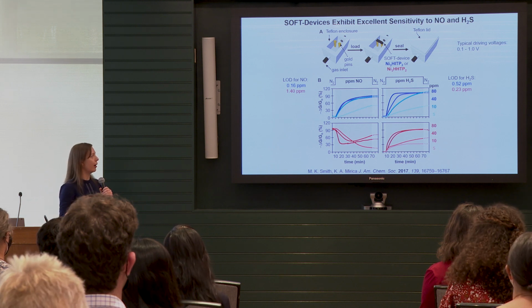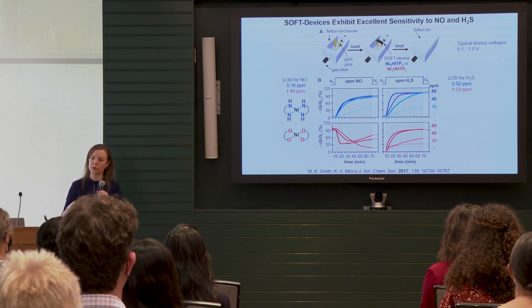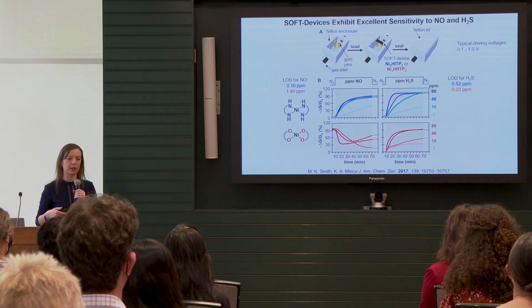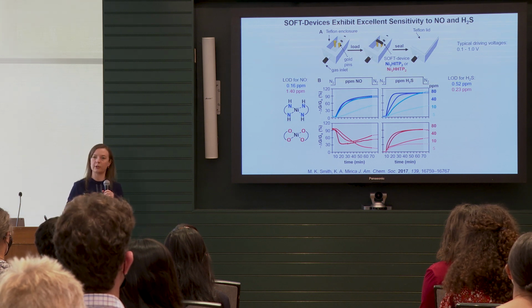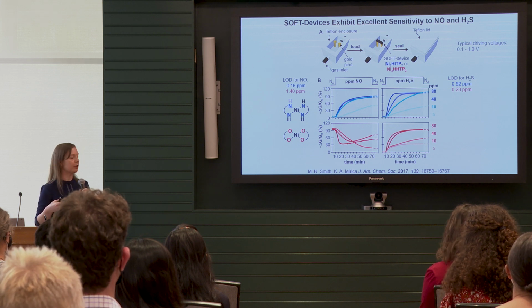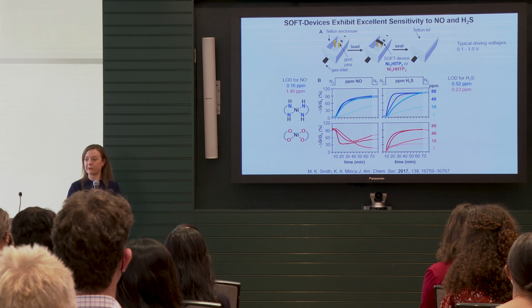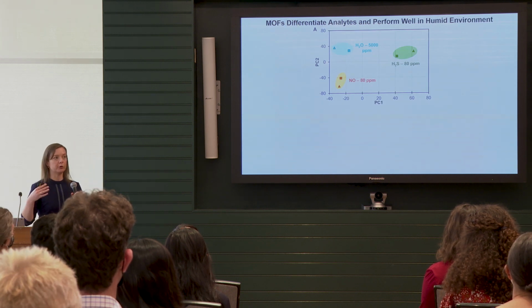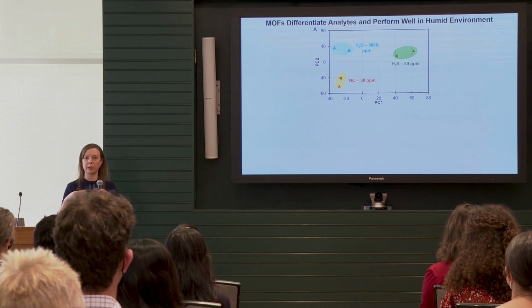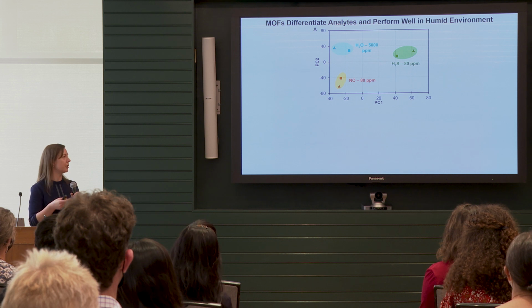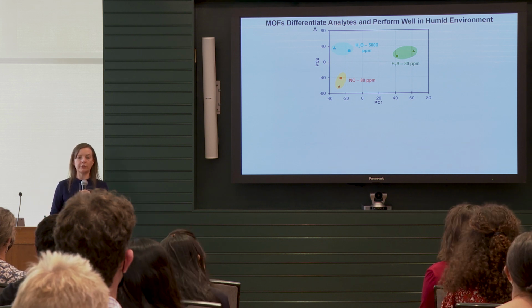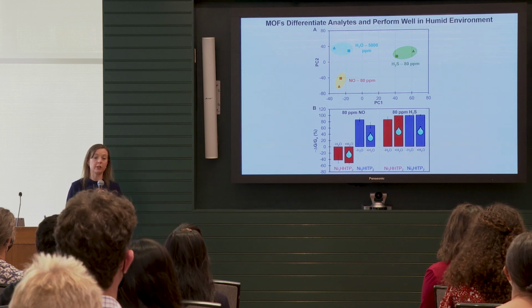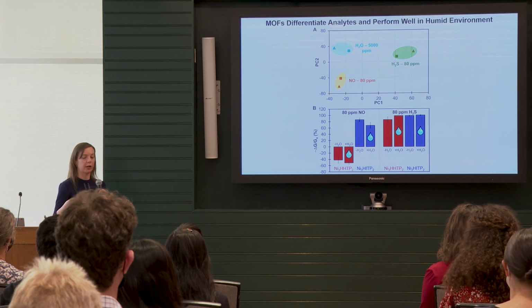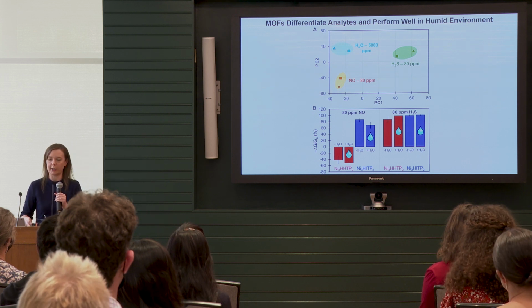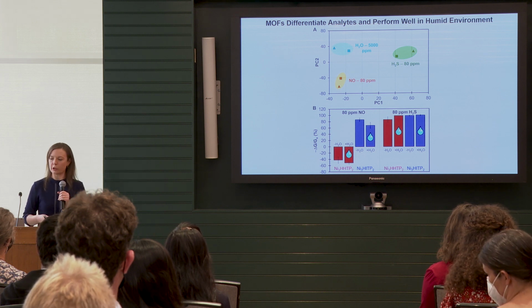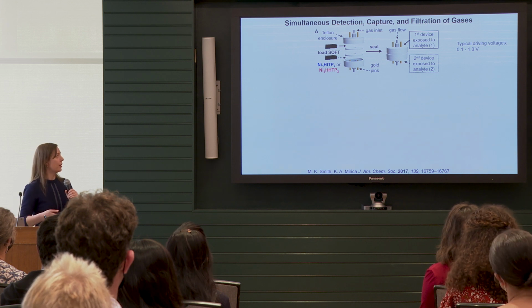The response itself for two different materials that we probed, two different frameworks that have the same metal but different heteroatomic crosslinks, the directionality of the response tells us something about the semiconductive properties of these materials. And having an array of two materials enables us to differentiate these gases from each other and to deconvolute the response of this array, and to begin to do some differentiation with some partial selectivity of each sensor to each analyte. So we're able to achieve sensing function, and we're able to maintain sensing function in the presence of humidity. If we humidify our gas stream, we're able to still sense, which is good for practical applications down the road.